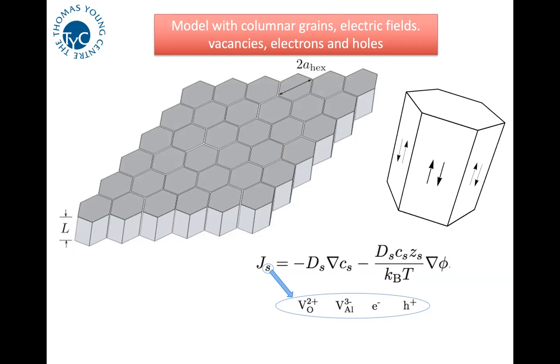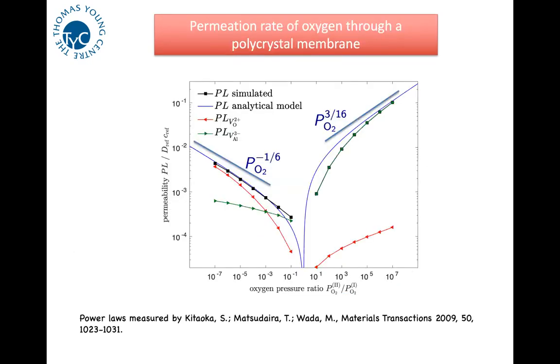But I just want to show you the bottom line, which was this graph, which is the asymptotic steady state situation where the currents are more or less stable. This was actually the assumption in Wagner's formula. And there is also in this situation some interesting power law behavior. This was measured by a Japanese group there who showed that the power law, this is a power law that describes the flux of oxygen essentially. This depends on the chemical potential of the oxygen outside the scale compared to the inside.